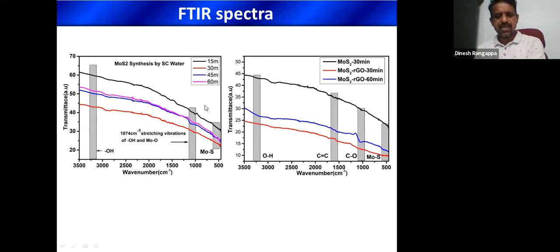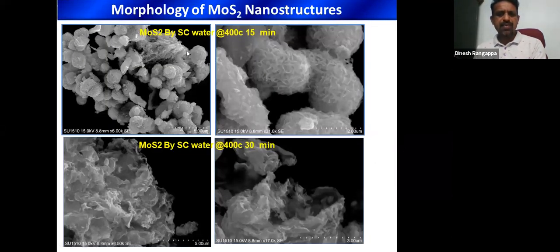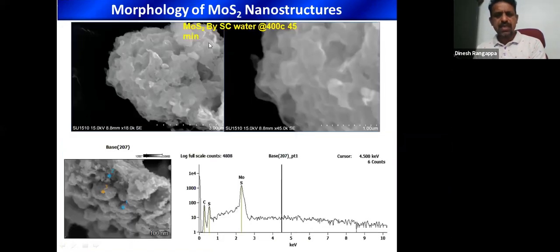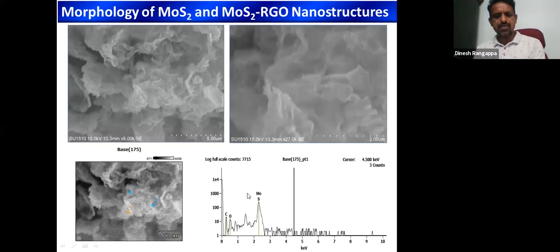So this is the FTIR result you can see, and the morphology of molybdenum disulfide nanostructure. You can see nanosheets, hierarchically organized nanosheet structure, which is synthesized at 15 minutes and 30 minutes under the supercritical fluid process. Then we confirmed the purity of molybdenum disulfide by measuring EDAX, and it shows only molybdenum disulfide without any impurities.